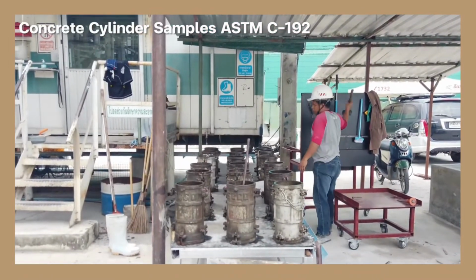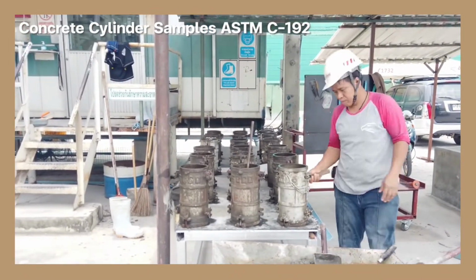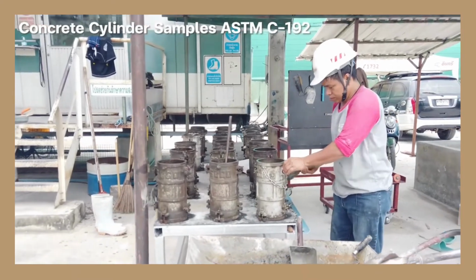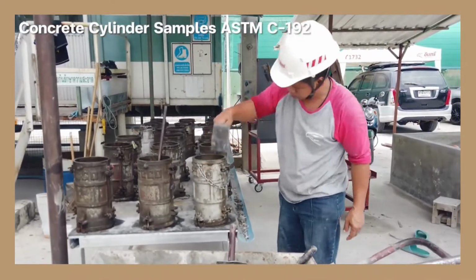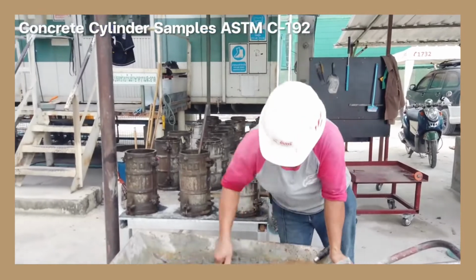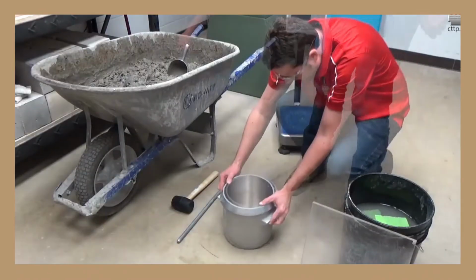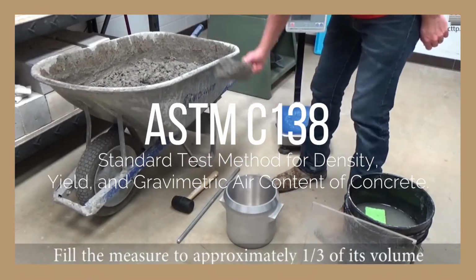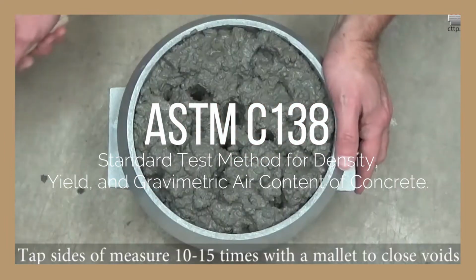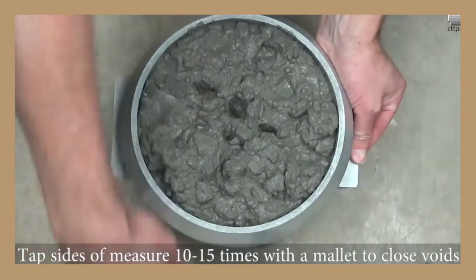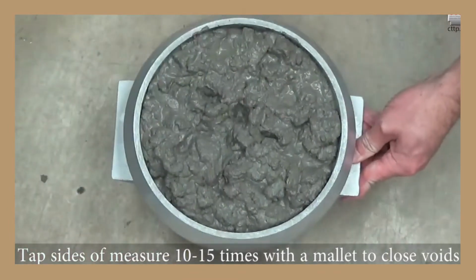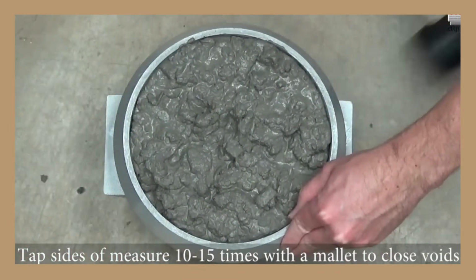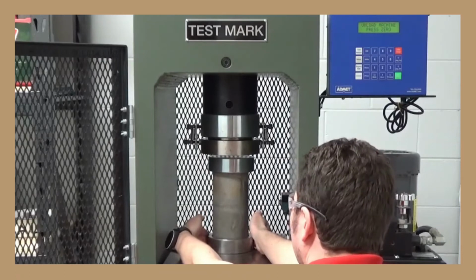Each specimen will be cured for 7 days, 14 days, and 28 days before subjecting to different mechanical properties tests. Before the necessary tests needed, each concrete mix must first undergo on a test conforming to ASTM C138, known as a standard test method for density, yield, and air content of concrete, since the study also aims to attain a potential lightweight material. To fully determine its workability, the mechanical properties shall be obtained.